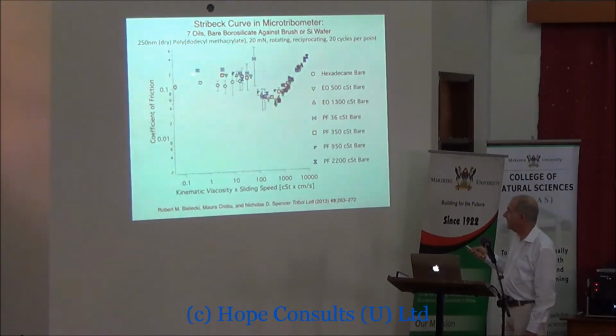And the viscosity is now in the x-axis, so we can plot all of these on the same graph. And these numbers here just show the viscosity in centistokes. Hexadecane is about 4 centistokes, so it's not very viscous. And then we have some oils which have higher viscosity. But it all goes nicely on a single curve. And out here is the hydrodynamic regime where we've got the hydrodynamic lift caused by the viscosity of the oil. So that's just oil and 2 hard surfaces with no brushes.